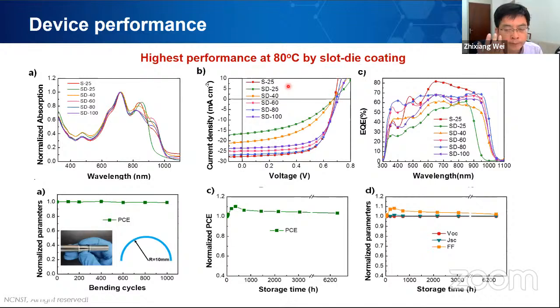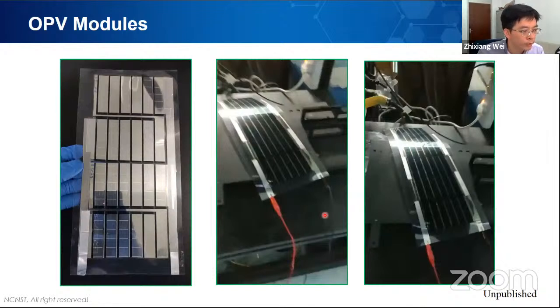These kinds of solar cells, because they are very thin layers, show high flexibility after bending at different bending radii, for example bending 1,000 times at a radius of 10 millimeters. You can see the PCE is really stable. Also the shelf-time stability is quite good. If you put the solar cells there and test their performance, it is quite stable. In the future we will further increase the stability by encapsulation or by interface modification. We want to further improve their light stability. This is the modules we can show in your lab.